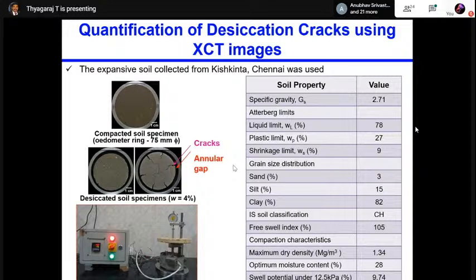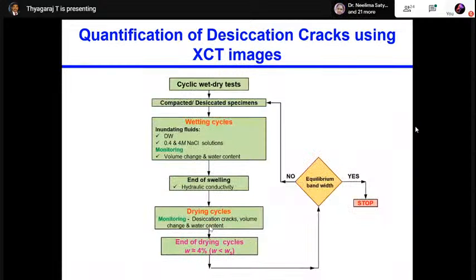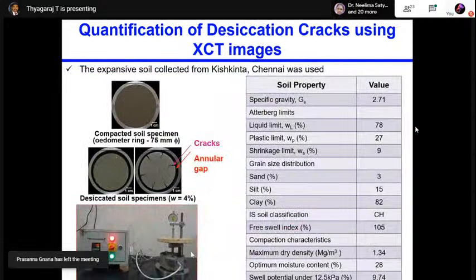You can see in this slide, we have compacted the soil in the oedometer ring, and when we dried it, you can see that during the first drying there are not many cracks, only the annular gap was there, the soil was shrunken. Whereas during the subsequent drying, you can see that there is an annular gap and crack formation. So both are there. So we have used this setup for carrying out the wetting and drying cycles.